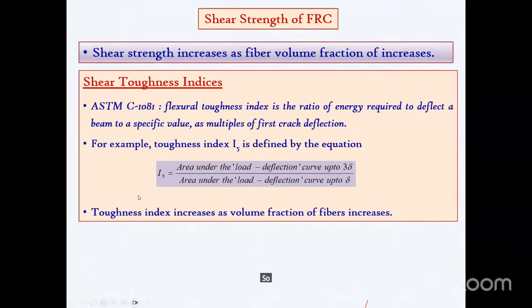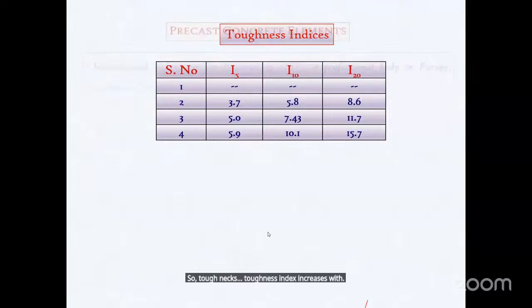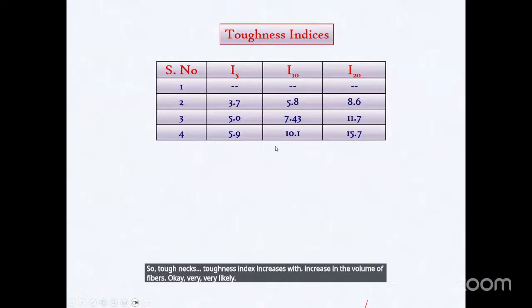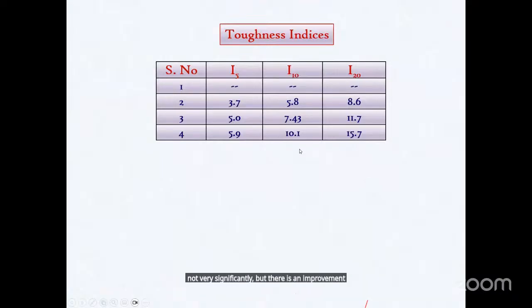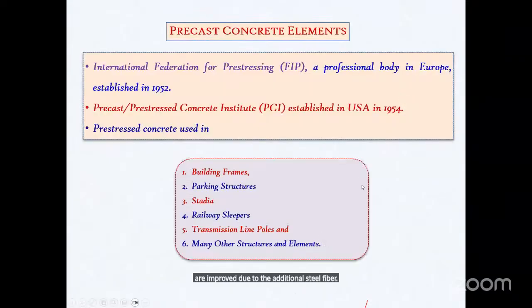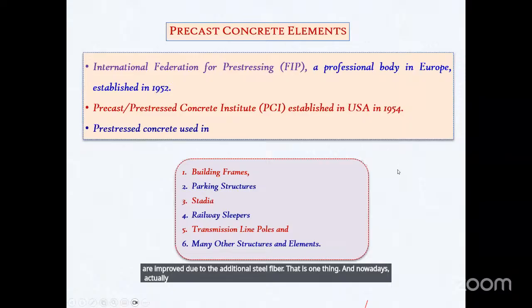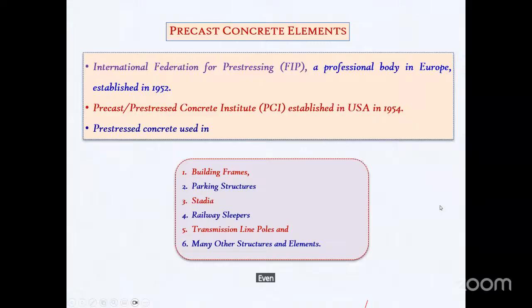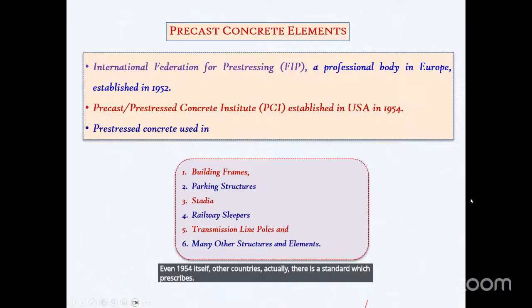So the toughness index increases with increase in the volume of fibers. Very lightly, not very significantly, but there is an improvement. Ductility is improved due to the addition of steel fiber. That is one thing. And nowadays, understanding the precast system is very important, because even in 1954, in other countries, there is a standard which prescribes the use of precast or pre-stress systems. Precast systems are always accompanied with pre-stressing systems. Pre-stressing and precast systems go together.